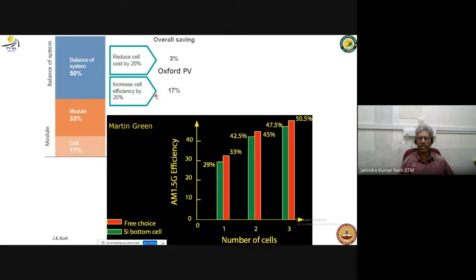That's why everybody is going towards crystalline silicon solar cells. And not only crystalline silicon, multi-crystalline silicon is also going out of the market. Really high quality crystalline silicon, monosilicon, is now what's being used, because everybody wants to go for high efficiency. But then that's why people want to know how to make a tandem cell with this crystalline silicon. Then you get more and more efficiency. This was explained by Martin Green, who once calculated that you can go up to almost 50% if you have 3 junctions. But people are trying only up to 2 junctions, where you can get around 40%.